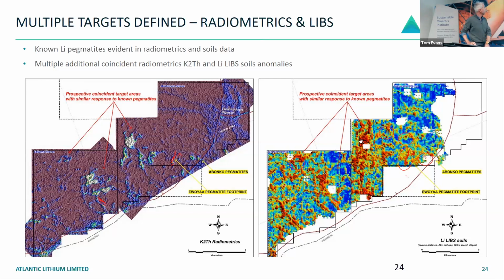They do appear, however, when you look at the LIBS analysis, there's the lithium in soils. So you can see here, that's the Afrangwa granitoid. And then you see this very strong line running up and down there. That's actually drainage. And here, sorry, you can see the Ewoyaa deposit. So that actually does highlight in the soils. We also pick it up as spot highs in tin, and it has a coincident rubidium anomaly in soils. So we use a combination of soils for lithium, tin, rubidium, potassium, thorium lows, in combination with radiometrics to circle areas of interest, and then to go onto the ground to the next stage, which is mapping and auger.